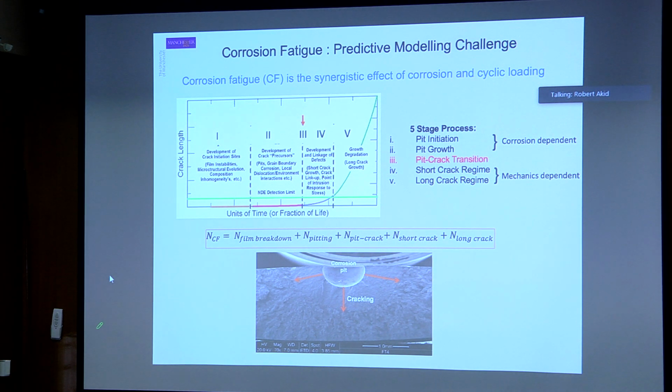These pits are generated electrochemically, so they produce quite a rough surface on the inside, and that is different to the modelling of a smooth hemispherical defect, and we've noticed that. But you're absolutely right.